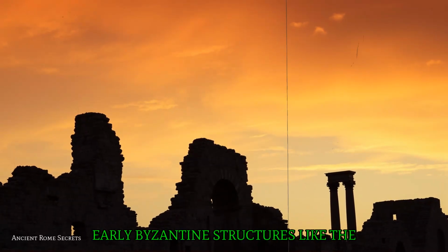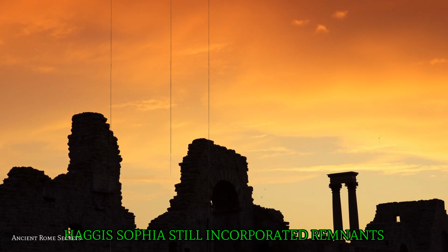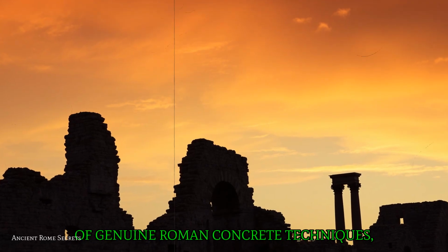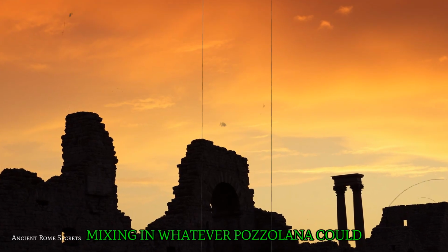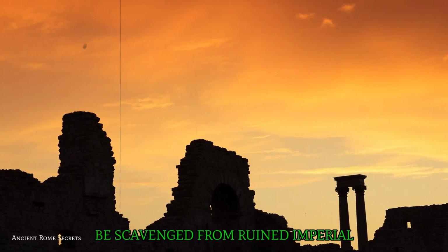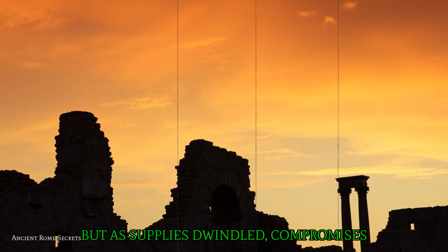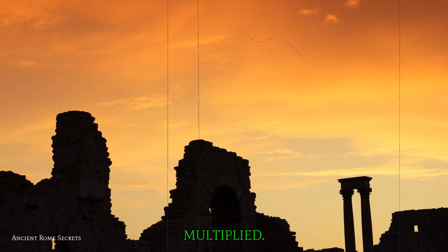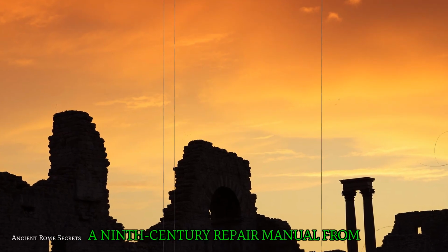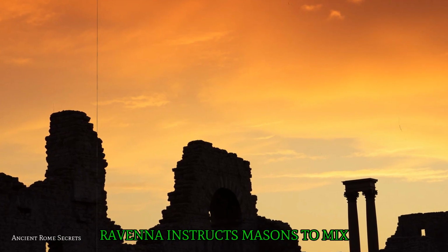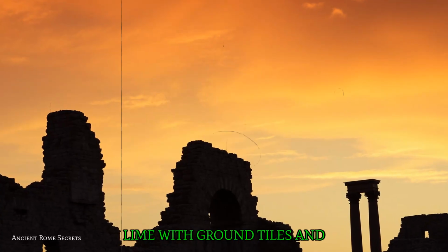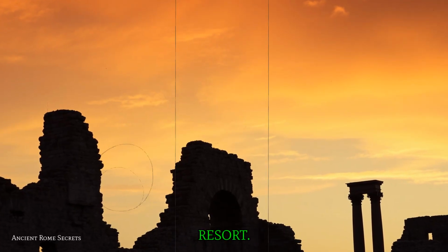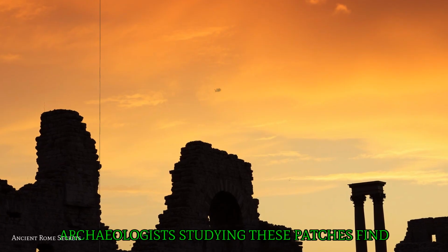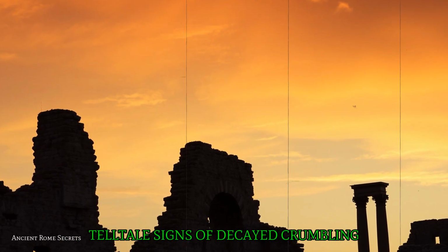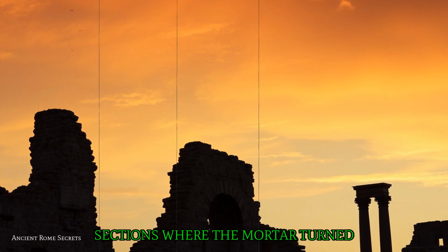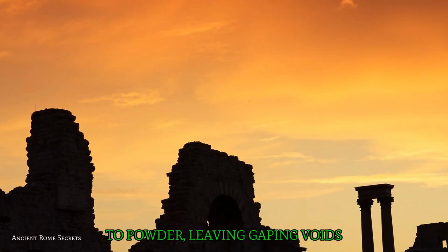Early Byzantine structures like the Hagia Sophia still incorporated remnants of genuine Roman concrete techniques, mixing in whatever Pozzolana could be scavenged from ruined imperial warehouses. But as supplies dwindled, compromises multiplied. A 9th century repair manual from Ravenna instructs masons to mix lime with ground tiles and brick dust as a last resort. Archaeologists studying these patches find telltale signs of decay, crumbling sections where the mortar turned to powder, leaving gaping voids between stones.